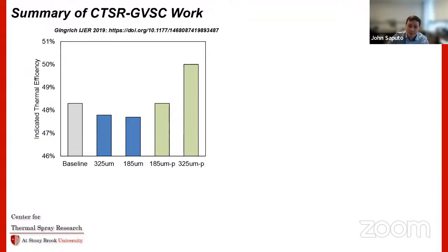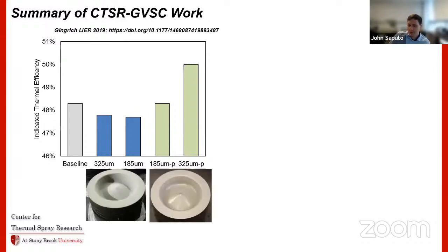So if you look at a baseline engine, it's about 48.5% efficiency. The first coatings we put in are these blue bars, and you can see that that drops down. So we're looking at about 185 micron thick coating and 325 micron thick coating that cause these performance degradations, which is kind of interesting. So when we first saw this, our first takeaway was, hey, these coatings are kind of rough. They're in the as-sprayed state.